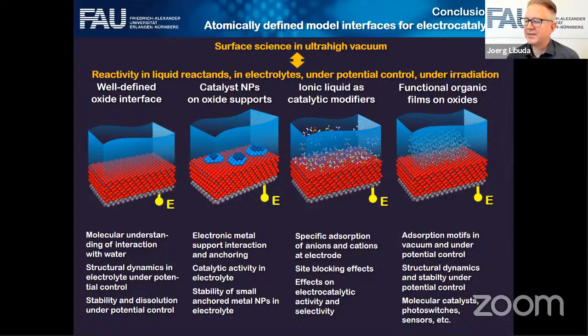The challenge with the electrochemical STM experiment is that it's orders of magnitude more complex than a UHV STM experiment. Normally you're extremely happy if you have a reasonable image at all. Typically these very detailed questions under very controlled conditions that you are used to answering in ultrahigh vacuum STM experiments are way beyond the electrochemical STM experiment. So this is basically the main message. It's really two worlds. It's not comparable in terms of stability, reproducibility, and range of conditions that you can apply. I wouldn't say it's unthinkable, but I think it's just difficult. Okay, thanks.